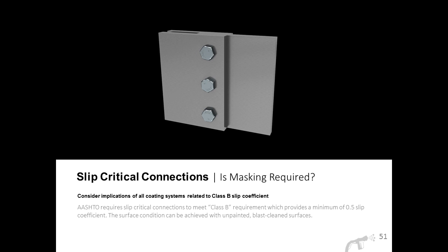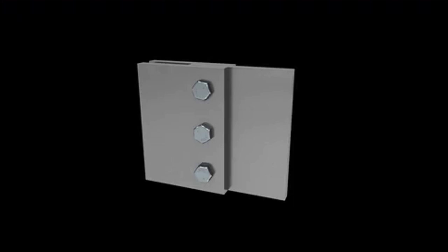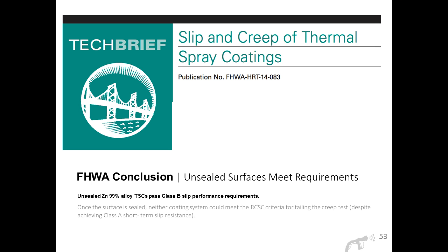According to FHWA, coating must be compatible with use in high-strength bolt connections. We covered that. A really important thing to take note of is that in 2014, FHWA published this tech brief on slip and creep of thermal spray coatings. The research was carried out by KTA, and ultimately their conclusion was that unsealed metallized surfaces meet Class B slip requirements.